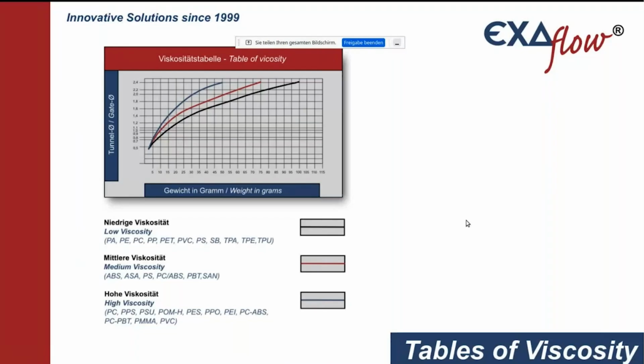So this is the viscosity table. If you need an idea for the gate itself, we have low viscosities, that's PA, PE, polycarbonate, polypropylene, and so on. Medium viscosity: ABS, ASA, polystyrol, and so on. And high viscosity, mostly the high-grade plastics like PEI, PSU, PPS, and PC, PBT, and so on.